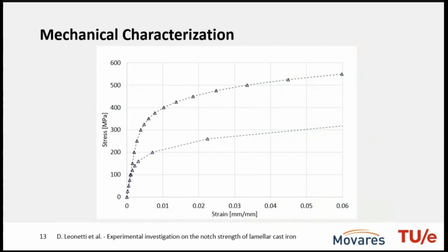But bringing the two curves together, you basically see 150 megapascal was about the ultimate tensile stress in tension. These curves are extrapolated, so you shouldn't take them as they are. But in fact, the tensile and compressive strengths are completely different. We have about 150 megapascal for tension and about 500 for compression.